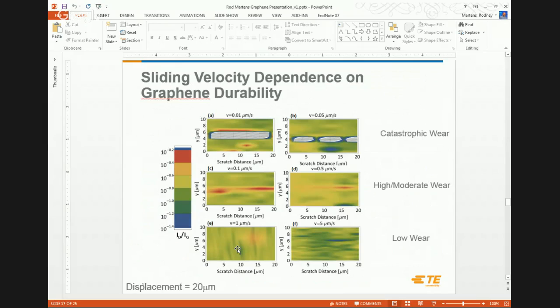Next exercise looked at the sliding velocity dependence on the durability of the graphene. And what was interesting here is that there is a very strong relationship with velocity, but the wear is worse at the lower velocities. And one hypothesis here is that at the slower velocity, there's longer residence time, so we can develop more adhesion between the tip and the graphene. But that work is ongoing, trying to figure out what's exactly going on there. And this would be more into the area of where Professor Jackson is looking at doing some modeling.